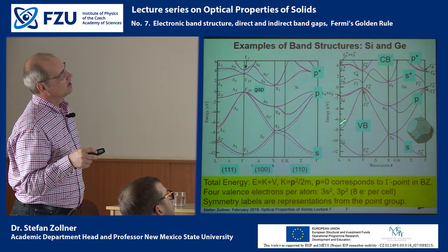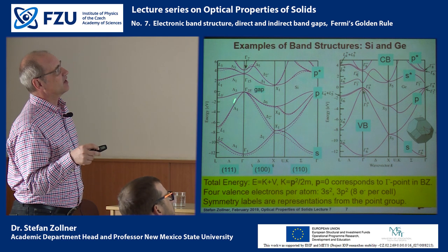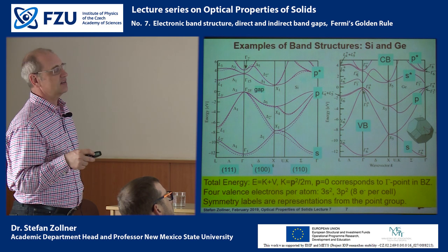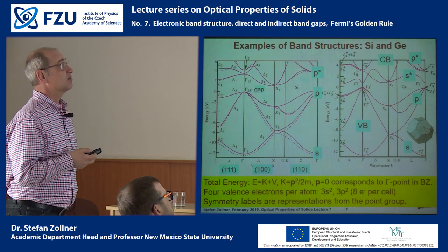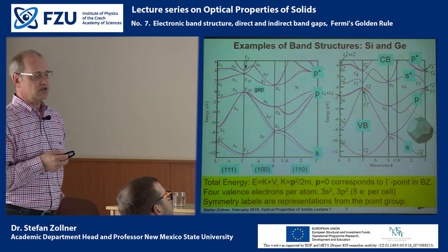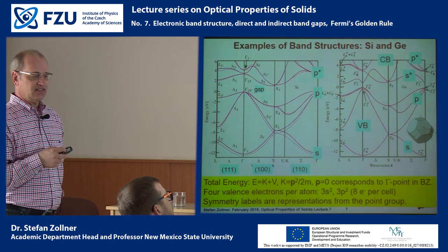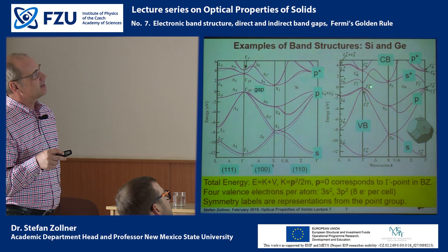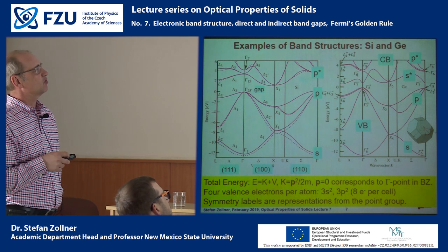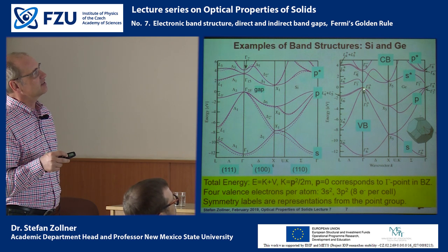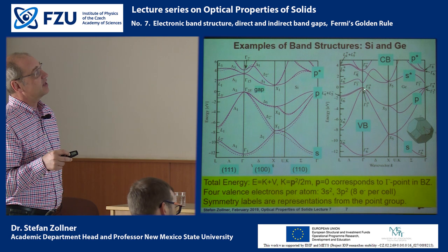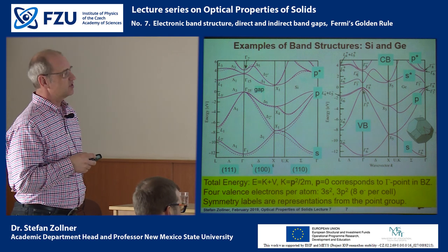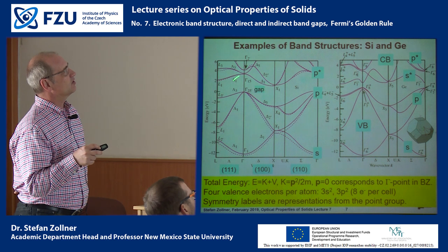So this is silicon. And the valence band of germanium is pretty much exactly the same as that of silicon, except that germanium has a higher Z, has a higher number of total electrons, and therefore the spin orbit splitting term L dot S, that's this Pauli term which comes out of the Dirac equation. The spin orbit splitting in germanium is approximately 0.3 electron volts, much larger than in silicon, and therefore in this band structure calculation, Chelikowsky and Cohen included the spin orbit splitting, and because we are going from a